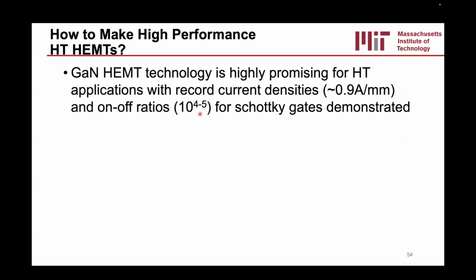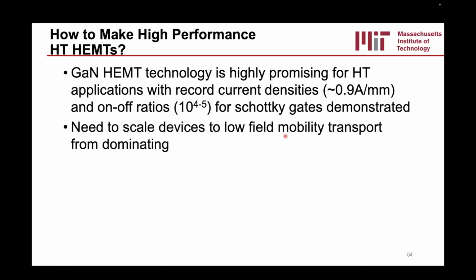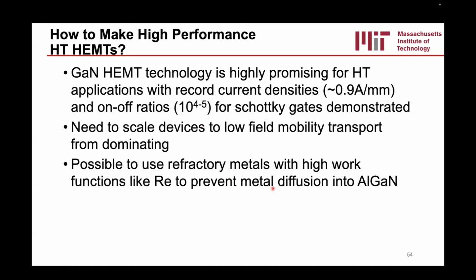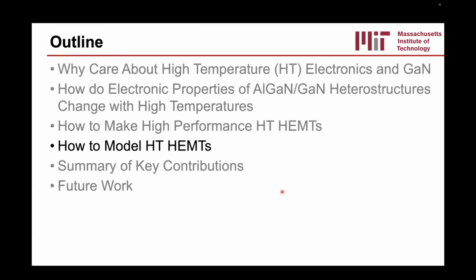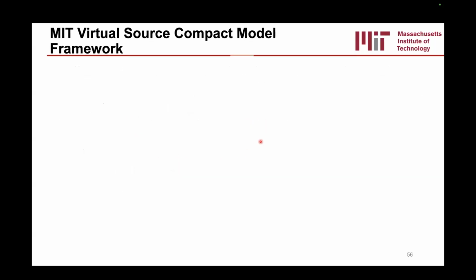All right, so now we know how to make a high performance, high temperature HEMT. You can get record, quote unquote, current densities of 0.9 amps per millimeter and 10 to the 4 or 5 on-off ratios for Schottky gates. You really got to scale it to prevent as much low field mobility transport as possible. And then you want to use refractory metals like rhenium to prevent diffusion of the metal into the AlGaN. All right, I'll end the very brief slide here with a few slides on modeling these high temperature HEMTs.